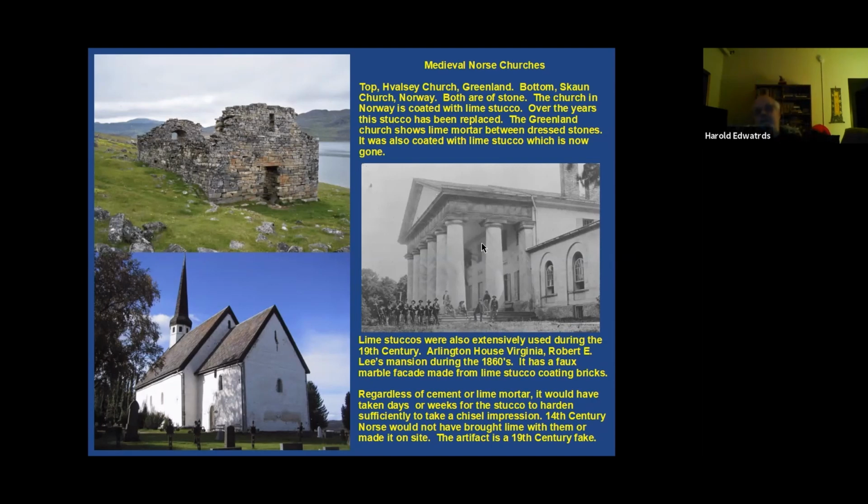Regardless of whether this was made of cement or lime mortar, it would have taken days or weeks for the stucco to harden sufficiently to take a chisel impression. And furthermore, the 14th century Norse would not have brought with them barrels of lime, nor set up a lime kiln in the Kensington area. And I call this the kiss of death. This definitely shows the artifact is a fake. This alone shows it's a fake without looking at anything else.